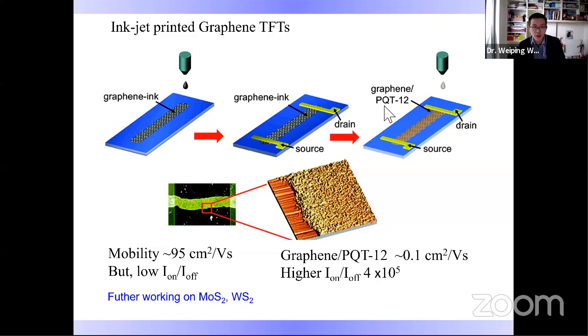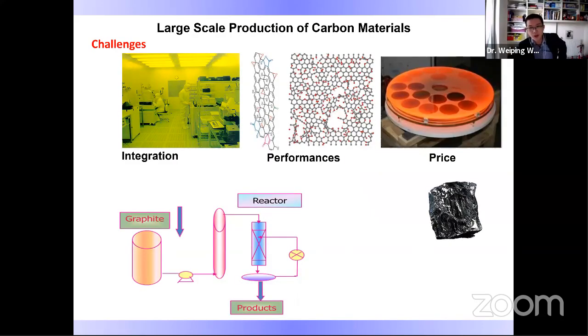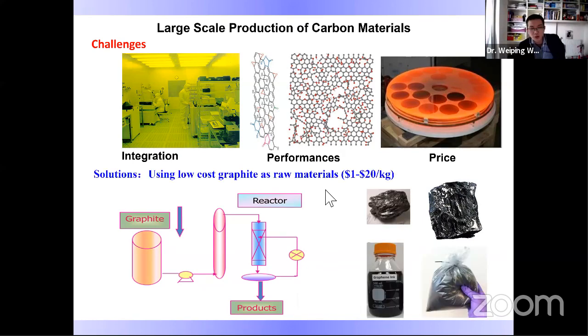We have demonstrated a very high mobility graphene transistor, but still a very low on-off ratio due to the zero band gap nature of graphene. A solution has been proposed by mixing PQT12 with graphene to gain an improved on-off ratio. This piece of work has been extended to MoS2 and WS2. If we compare this method with graphene oxide, which induces a high level of defects, and with the price of growing CVD graphene on wafers, this approach is very promising and very encouraging towards industrialization.